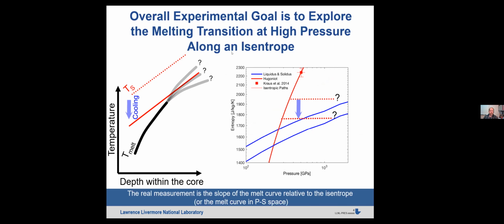Okay, so in the context of what this means for a planet, what we really tried to do is take the iron in these samples through the same thermodynamic path that the iron would follow during the convective process in the liquid outer core.